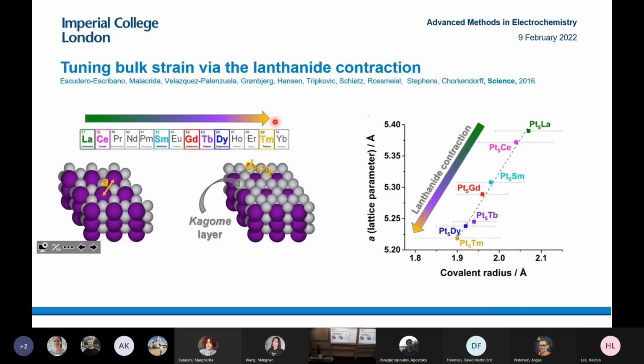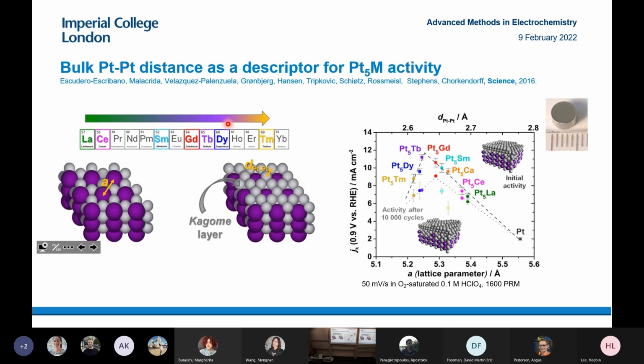Then we thought, okay, we've now looked at platinum yttrium, platinum gadolinium. What happens if we change the lanthanide atom? Because we thought in particular this would be interesting, because usually when you go further along the lanthanides, the lanthanide becomes much smaller. So we thought maybe this would be a way of tailoring the activity. And this is work done by Maria Escribano, who's now at Copenhagen University.